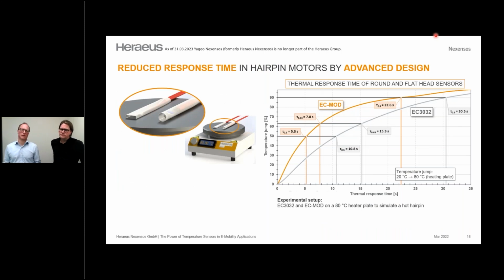When talking about thermal response time, it's always good to not only talk about theory, but also about practical results. What we did here in order to compare the round head versus the flat head on a hairpin-like situation is we made a kind of temperature jump test. We put the two different sensor types on top of a hot plate. That means having a temperature jump from room temperature to an 80 degree hot heater plate, and then looking at how fast the sensor reacts, how fast the signal changes going from room temperature to this elevated temperature, and how fast we can reach the 100% or the 90% accuracy. And this is what you see here on the right side. In gray is the standard round head element, and in orange you see the modified one, adapted for hairpin motors.